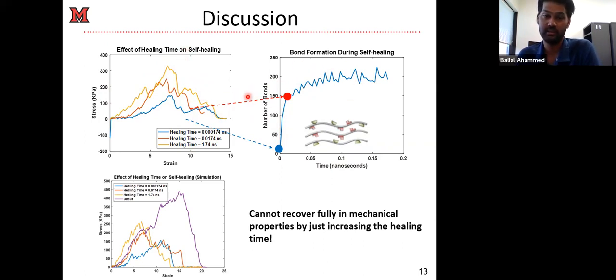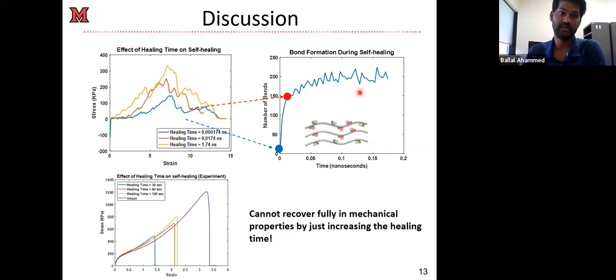So it explains how the materials recover with time, but it doesn't say anything about how the materials recover with the application of compressive forces. Another interesting thing is that the mechanical properties cannot be recovered fully by just increasing the healing time, because it gets flattened. So you need to come up with some other method to accelerate the self-healing process, which would increase the number of bond formations. So let's move forward.